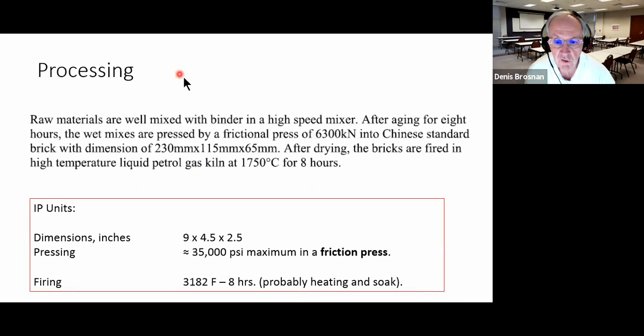Now, a comment on processing. So they were mixed well with binder in a high-speed mixer. Well, I hope so. And they used a friction press or impact press with a maximum impact force of 6,300 kilonewtons. I had to convert that into pounds per square inch, and that would say a maximum was about 35,000 due to the impact. That doesn't mean that the press reached that pressure, but typically in these presses, you'll give a light impact to de-air, have a little bit of dwell, and impact one or more times to get toward the final density.